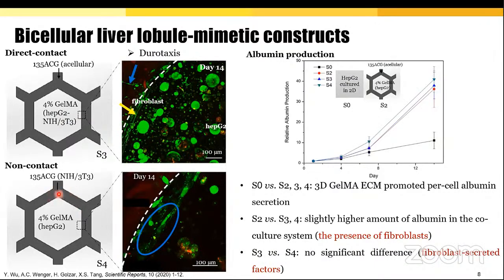In the non-contact system, fibroblasts were printed in the outer honeycomb and HepG2 cells were deposited in the inner cavities. Fibroblasts were found to proliferate and elongate in 135 ACG hydrogels and align along the boundary as well. Interestingly, the two types of cells migrated towards each other over time, and a direct intercellular contact at the boundary occurred as shown in the blue circle.